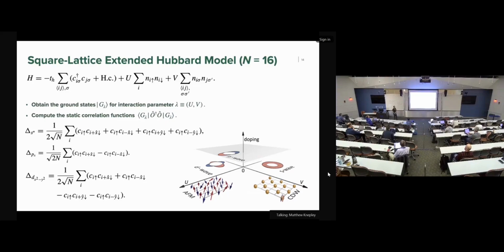kind of response. And it turns out if you have different possible linear superpositions based on the prefactors, they form what we call S wave, P wave, or D wave. So the idea is that if you have a Hubbard model with U and V terms and the ability to dope the materials, you can induce quantum phase transitions from, for example, an antiferromagnetic insulator to a charge density wave insulator, or to a superconducting state of different pairing symmetry. So that's the goal.